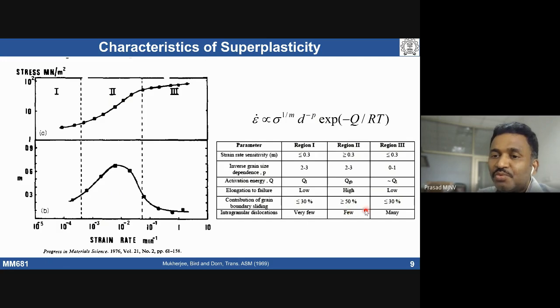So if we deform material at this strain rate, and if we stop it and see the microstructure, we rarely see presence of dislocations in region 1. If I deform material at this strain rate and look at the microstructure, we do see many dislocations. So in region 2 very few dislocations can be present in the material. So these are typical characteristics of a superplastic phenomenon.